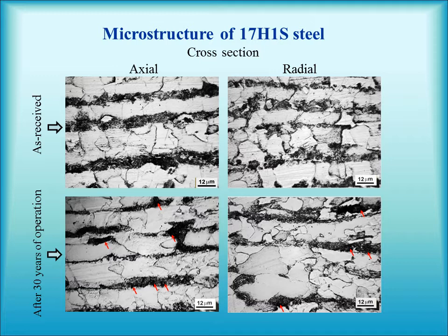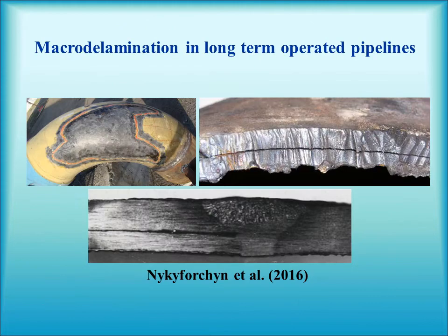Thus, pearlite becomes damaged with a well-developed network of defects, micro-delaminations, concentrated mainly along the borders with the ferritic bands. We can see the darkest areas of damaged pearlite in lower pictures indicated by arrows. Matching together, this delamination can reach significant sizes, like in the case shown on the figures. Such defects undoubtedly weaken the pipe wall and facilitate the fracture processes.